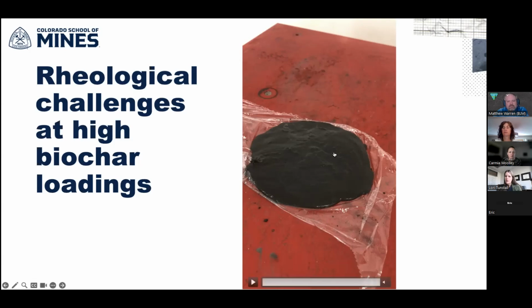Yep. So I will say at lower biochar loadings, you get conventional behavior. So it's only at these higher biochar loadings where we have a problem. And so for our interest, because we're really looking to get to carbon negative mixes, we're trying to solve the problem with higher biochar loading so that we can get that carbon neutrality or even negativity in these mixes. But any amount that you incorporate has an environmental benefit.